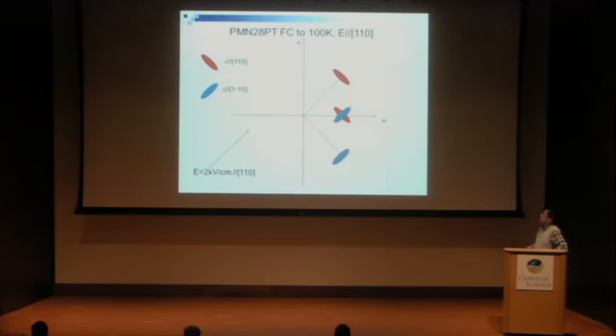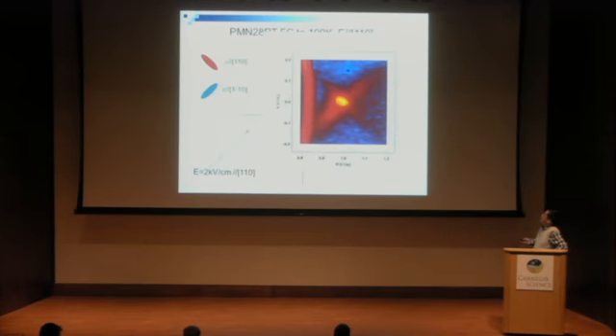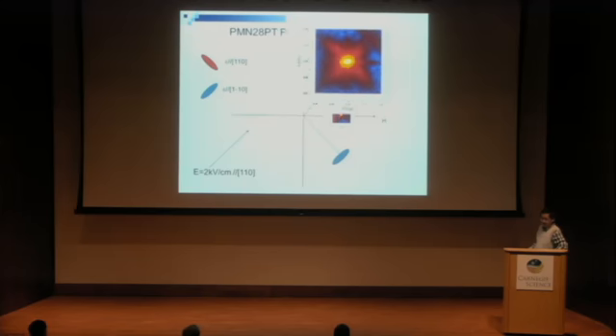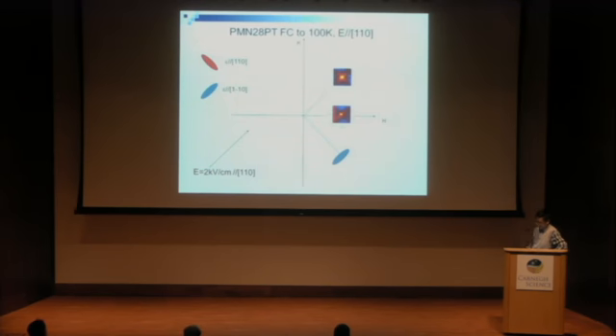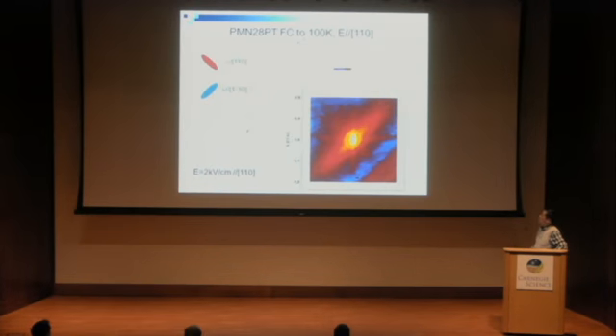And as we know, the diffuse scattering in relaxors is easily affected by an applied external field. For example, in this case, we applied a 2 kilovolt per centimeter electric field along the 110 direction. And then the diffuse scattering near the 100 Bragg peak is clearly asymmetric now. The blue wing seems much stronger than the red wing here. And near the 110 Bragg peak, the blue wing is also much enhanced, and it's almost the same intensity as the red wing here. And for the diffuse scattering near the 1-10 Bragg peak, the strong blue wing is even stronger and becomes dominant.